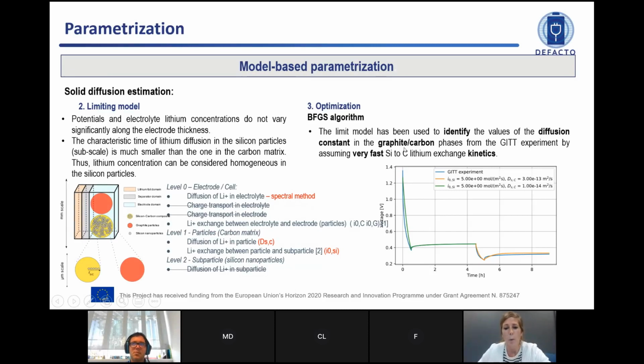constants. So what we did in this case is assume a very fast kinetic between the silicon and the composite, so we were able to identify the diffusion coefficient. So this is an example of how we used the models to improve the parametrization and therefore accelerate the experimental work.